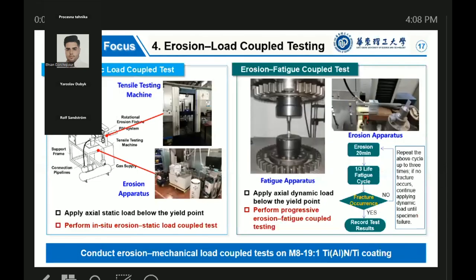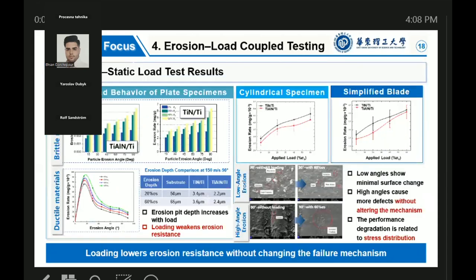The fourth part investigates erosion and mechanical load coupling. Using optimized coatings, we performed tests under static and dynamic loading to assess performance under combined erosion and stress. Applying static load increased both the erosion rate and the erosion depth, and similar trends were also found in the ductile substrate. SEM observations showed that the surface morphology changed little at low angles, but more defects appeared at high angles without altering the layer-by-layer failure mechanism.